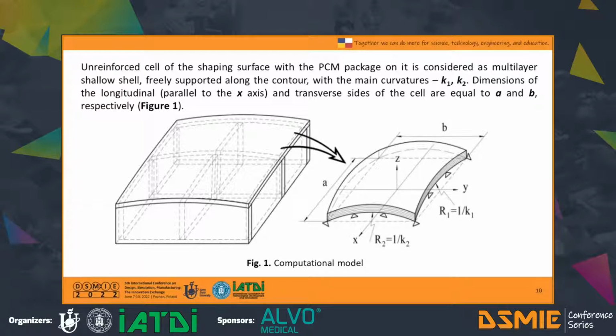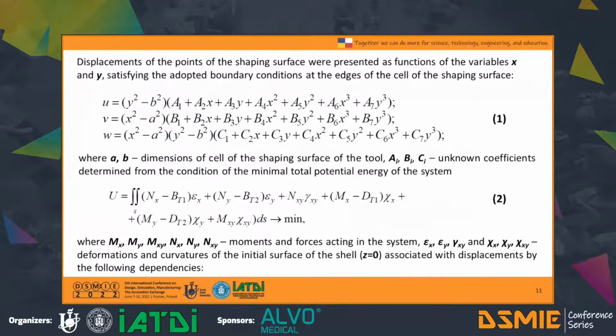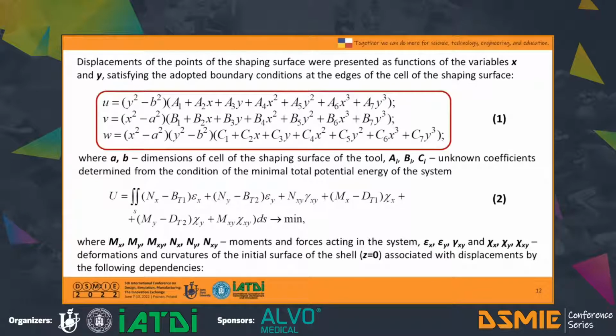This slide presents a computational model for this research. Deflection of the unsupported part of the molding tool is determined by solving the problem of thermoelasticity of a multi-layer shallow shell with the use of the Reissner-Timoshenko variational approach. Displacements of the points of the shaping surface were presented as functions of the variables x and y. Unknown coefficients A, B, C with index i are determined from the condition of the minimal total potential energy for the system.